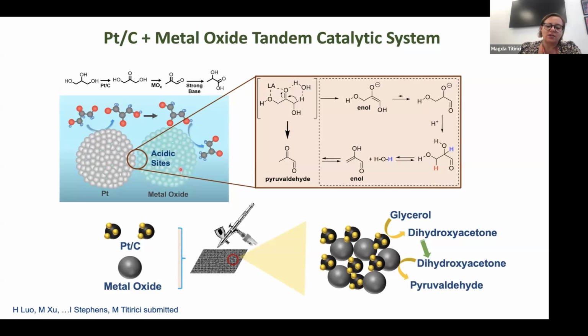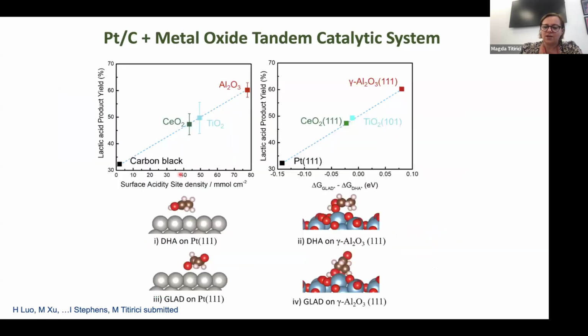So we supported platinum on different metal oxides with a lot of acid groups, and we looked at lactic acid production, and we saw that that scales very nicely with the amount of acidic groups on the surface of the catalyst. This fitted also very nicely with DFT calculations, where if you take the Gibbs free energy of glyceraldehyde, the product you don't want to form, minus the Gibbs free energy of dihydroxyacetone, this fits very nicely also to lactic acid production.